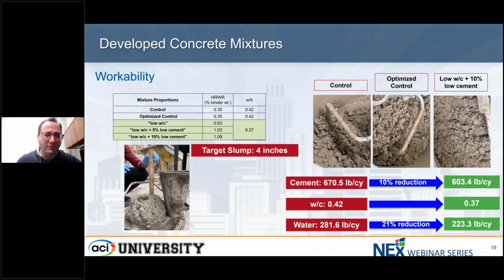Here are the mixed designs we have. So we have, as I said, control and optimized control at the initial point. The difference between those two is that in the optimized control, we optimize the aggregate system. Both of them have a water binder ratio of 0.42. Then we have low water cement ratio with 0.37 water cement. Then we reduce cement by 5% for that mix and by 10% for that mix.